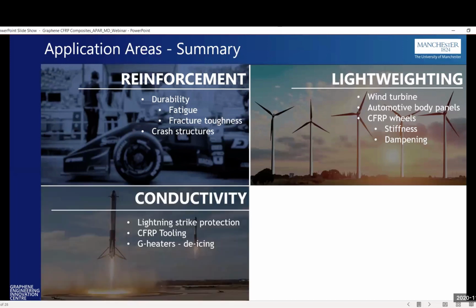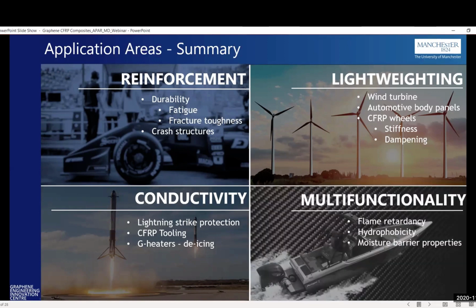Conductivity, for example, both thermal and electrical conductivity, plays an important role when it comes to graphene-based materials. Of course, you have seen commercial applications where graphene is being used or tested for lightning strike protection. Also, graphene-based heaters are being developed for de-icing applications, and there is a big spearhead being developed within the Graphene Flagship concentrating on this application. And multifunctionality is obviously another additional benefit: apart from the mechanical and lightweighting benefits, you are looking to improve the flame retardancy and hydrophobicity of the entire composite.